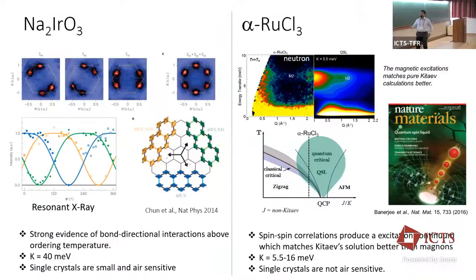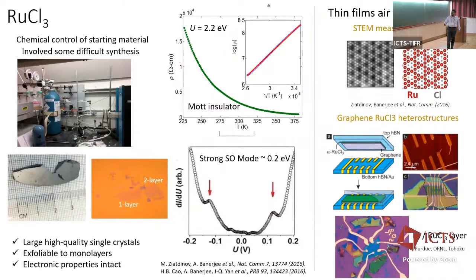To answer that question, two classes of materials have really been studied. Sodium iridate, where they basically showed that you have strong bond-directional interactions. And then we started working on alpha ruthenium trichloride. First measurements were in powder, where we started seeing some of these scattering spectra. It took us a long time to get this material correct. In fact, we spent like 2 years in chemistry labs to really get the right material, which let us grow very nice single crystals, 1 gram, 2 gram.